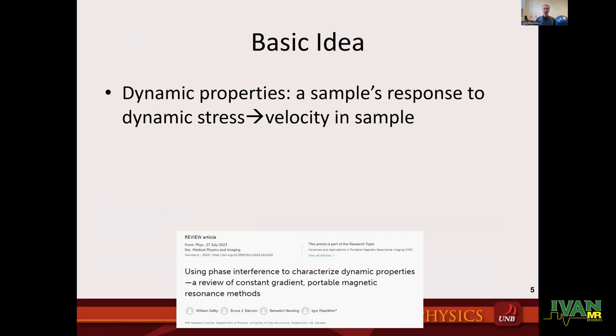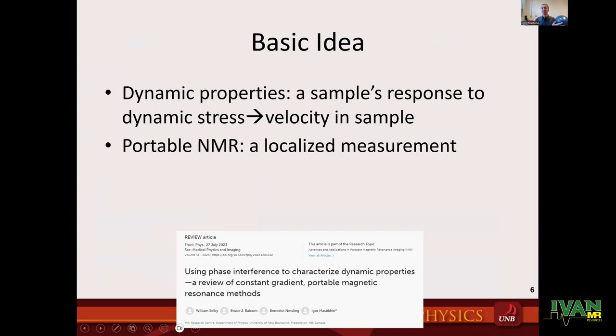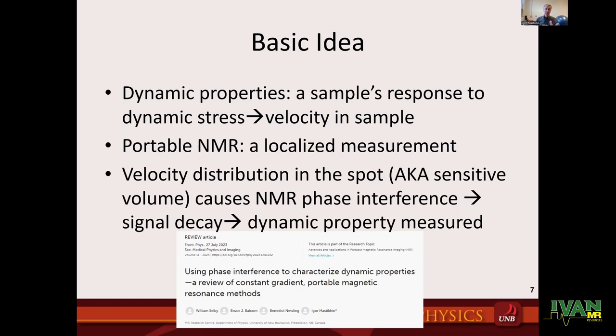So the basic idea of the talk is as follows. What are dynamic properties? Well, it is a sample response to dynamic stress. You shake your sample and particles begin to move. You have velocity in the sample, and then you detect that velocity. Portable NMR is essentially a localized measurement with a portable device, so your signal comes from a spot located in your sample. When you have velocity present in that spot, you will have phase proportional to the velocity. If you have a distribution of velocities, you have NMR phase interference, and that will result in a signal decay, which will let you extract information about the dynamic property of interest. So the basic idea is quite simple, and I'll go over that along the way.